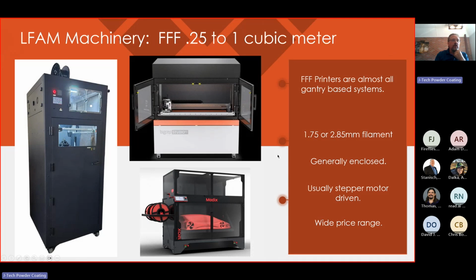So in the 1/4 to 1 cubic meter range, these are typically gantry style machines. I mean, there are some Delta configuration printers, but I don't know of any that are larger than 1/4 cubic meter. All FFF machines are similar in how the part is created. Material is laid down layer by layer through a heated nozzle, same way a desktop machine works. The difference is really in the extrusion rate. Desktops typically extrude 10 to 30 cubic millimeters per second, while in LFAM, the extrusion rate is up to 200 cubic millimeters per second. There are some very well-known names in this segment, such as Stratasys, Big Rep, and Modix.